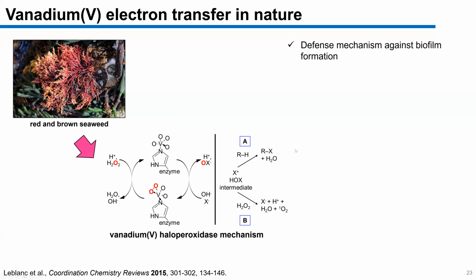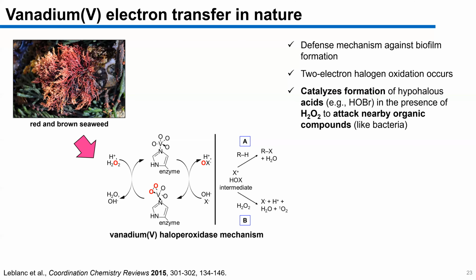This enzyme is one of the first examples, actually, of vanadium being incorporated into biological structures. And this enzyme serves as a defense mechanism against biofilm formation. So what happens is you have a two-electron halogen oxidation process. The enzyme is going to combine with hydrogen peroxide nearby and a nearby halogen, so bromide, for example, and you are forming a hypohalous acid, for example hypobromous acid, this HOX notation here.